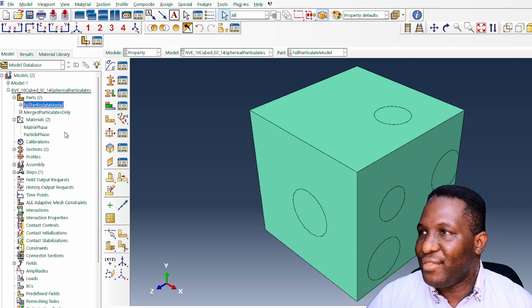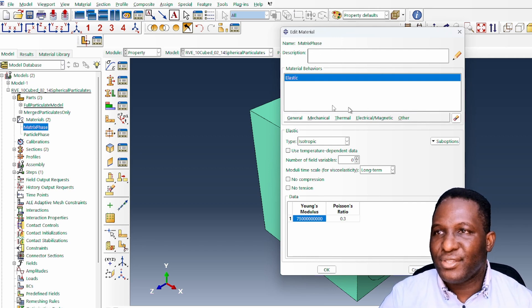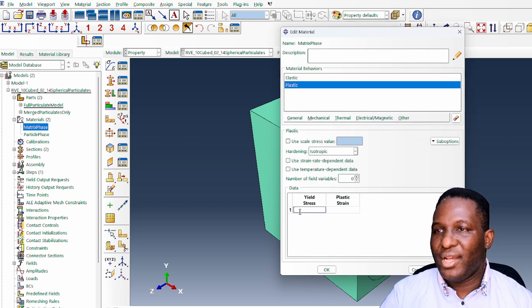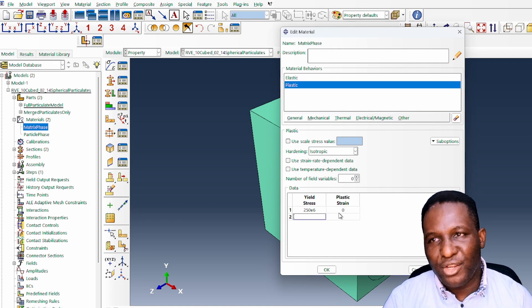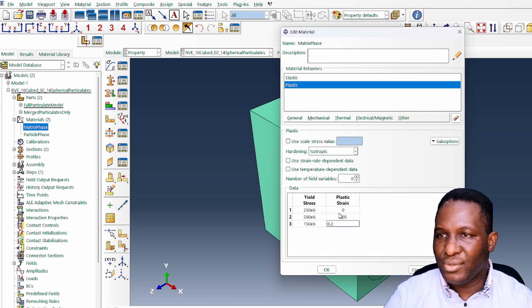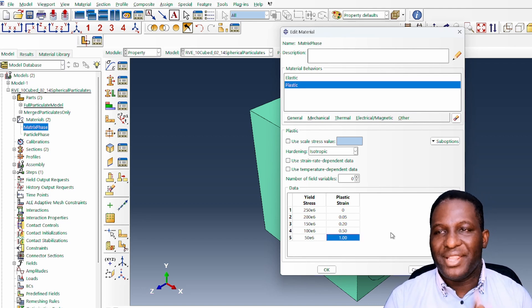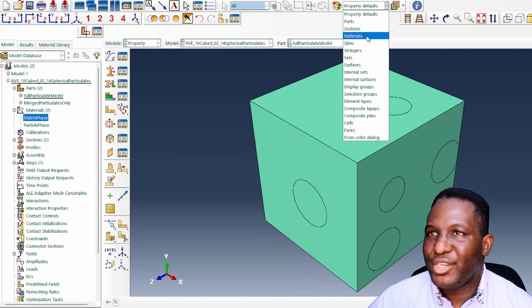The matrix material currently only has elastic properties, but since we want some plasticity, I'm going to add elastic-plastic behavior for the aluminium. The Young's modulus is set with a yield strength of 250 MPa, and then some post-yield behavior: 200 MPa at 0.05 strain, 150 MPa at 0.20, 100 MPa at 0.50, and 50 MPa at 1.00. This gives some kind of post-yield softening. This elastic-plastic behavior will be adequate, though of course you can use all available material models.